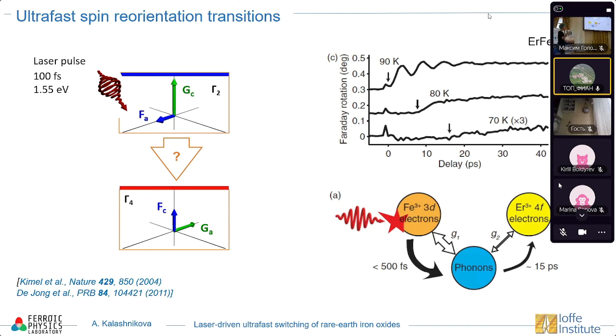And then, because of the coupling, which is rather slow on the time scale of several tens of picoseconds or so, between phonons and 4f electrons of rare earths, in this case erbium, this is basically when the transition happens. Because of this coupling, the different crystal field split levels of rare earths are repopulated, the magnetic moment changes, and as a result, a spin orientation transition occurs. So there is some kind of a delay or bottleneck.